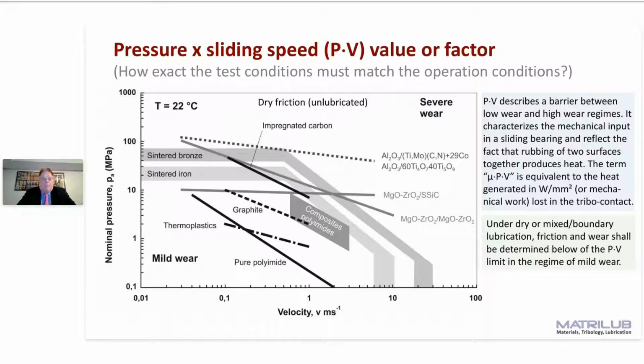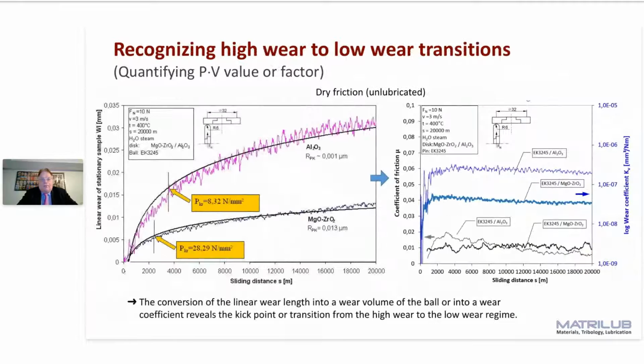This means you do not need exactly the operating conditions of your application, but you must be sure that during your test you are in the mild wear region of the couple in respect to the application. When your load or your speed or your PV value in your test equipment is too high and you are under severe wear, you can never have results which can be transferred to an application. So it is important to know these PV values of a material, of a couple, of a lubricant, and you must not have exactly the same PV value in your tribometer. You must at least be in the region of mild or low wear.